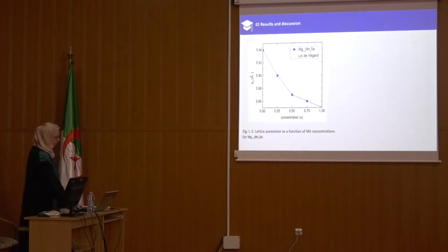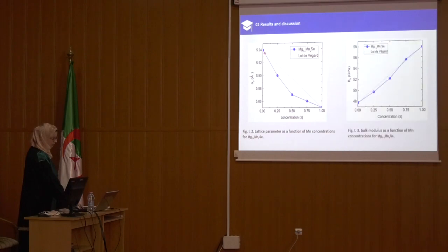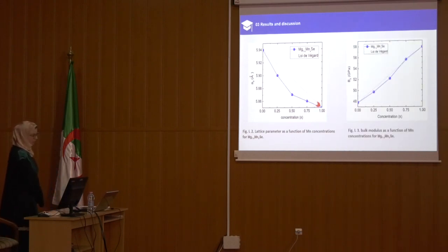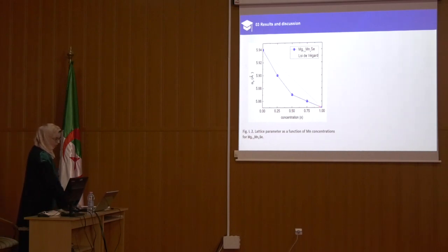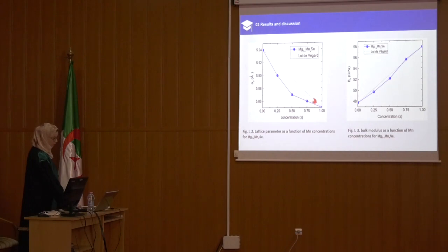are very close to the experimental values and in good agreement with theoretical calculations. Here we present the lattice parameter as a function of manganese concentration for MgSe. There is a decrease in the lattice constant with increasing manganese concentration, because the ionic radius of manganese is smaller compared to the Mg atom.